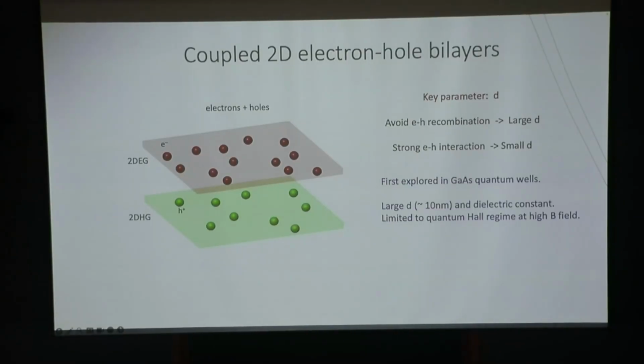So in order to see interesting things, people tried to go to the quantum Hall regime at very high magnetic field, and many interesting things were indeed observed. So what we want to ask is, is it possible to actually stabilize strongly interacting excitons at zero magnetic field? Basically a conventional exciton. And in order to do that, it's very important to control the distance at really atomic precision. Depending on what the optimal condition is, you might want just one atomic layer or two atomic layers, or maybe a few atomic layers to optimize the system.